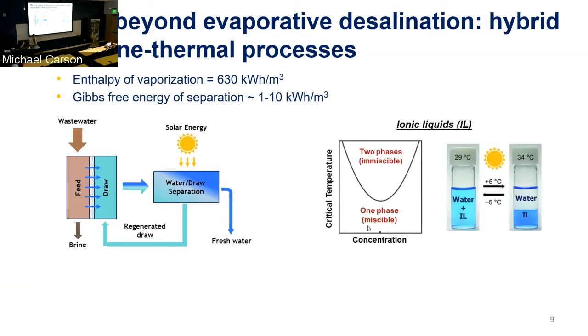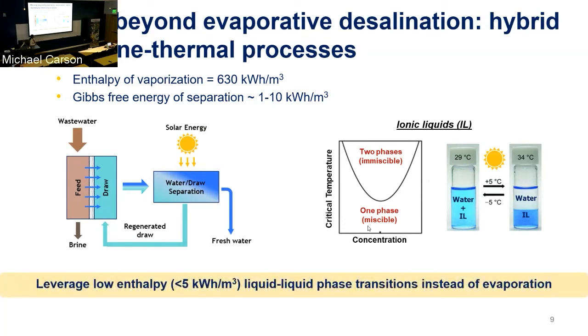So we use these thermally responsive ionic liquids, which exhibit a very interesting phase behavior in water. So they have a critical temperature above which they will phase separate from the water. At room temperature, they're fully mixed with the water, as you can see here. But if we heat that up by about 5 or 10 degrees Celsius, you can get the two layers to phase separate. And so really here, what we're saying is let's look at new phase transitions beyond the more traditional liquid vapor phase transition. So these are liquid-liquid phase transitions to really enable us to do desalination.